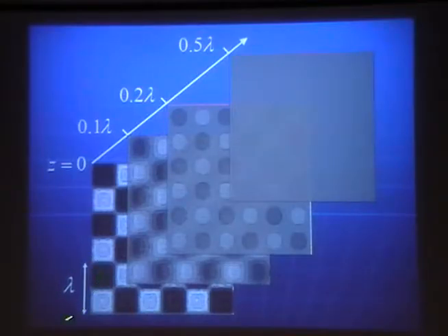So let's imagine that lambda is just 1 micrometer. It means if you are separated by half a micron from the surface, you will not see any variation of the azimuthal angle, but the orientation is pretty much uniform. So this is completely parallel with the surface potential problem.